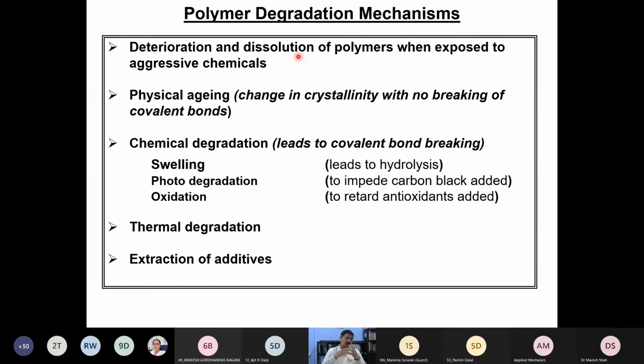Apart from that, you do have physical aging. Physical aging means you do not break the covalent bonds between the monomers, but as a result of the physical aging, your crystallinity is going to change. I always give an analogy between the aging of a polymer and the aging of a human being. The physical aging of a human being also starts anywhere between 30 to 35 years, but you don't see a substantial change in your body or physical activity till you cross 50-55 years. This is the process where the crystallinity increases within a polymer.